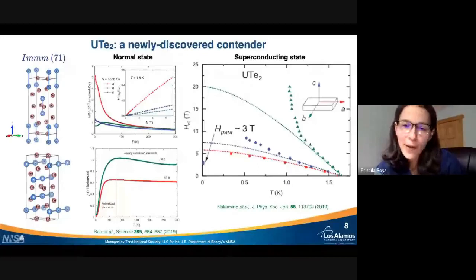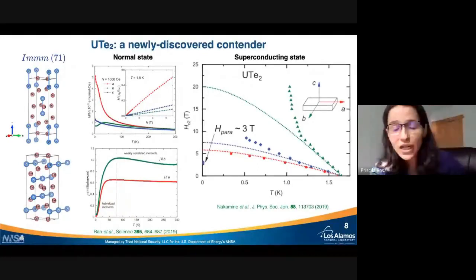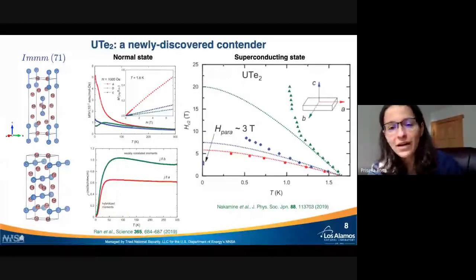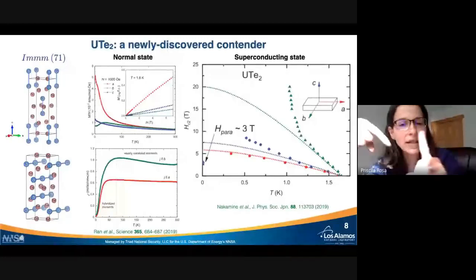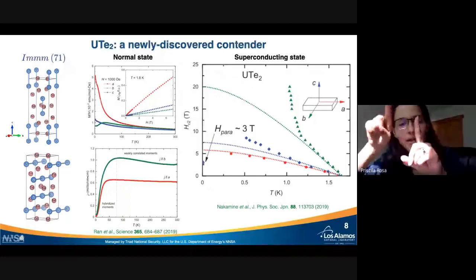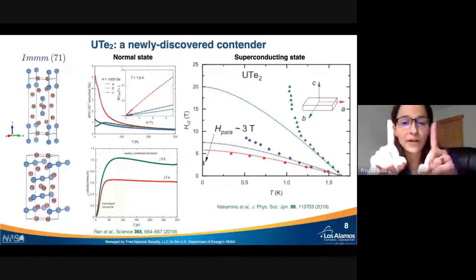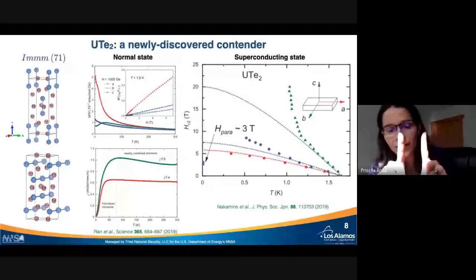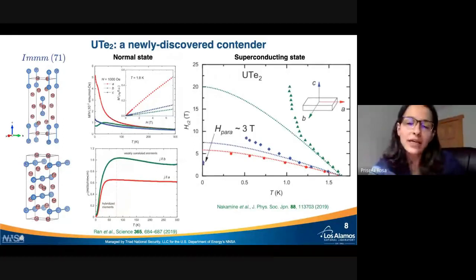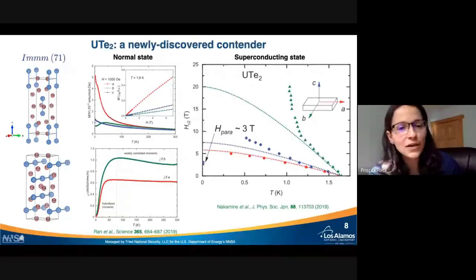Here is the HC2 versus temperature for various directions, and if you look at the B-axis, it goes almost vertical at about 1.2 Kelvin, really showing that this superconducting material is not limited by the Pauli limit, meaning that the Pauli limit for a singlet is when those spins start to flip, but for a spin triplet superconductor, that doesn't matter. So this is really a strong indication that this is a spin triplet superconductor. And if you remember the first slide I showed you, spin triplet superconductors are actually contenders for topological superconductivity.